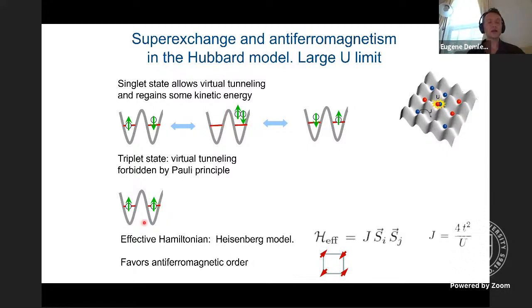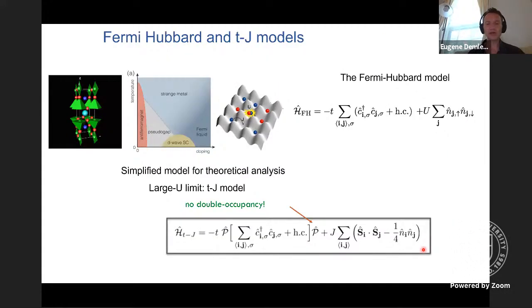On the other hand, when spins are aligned, then we notice immediately that double occupancies are just not possible by the Pauli principle, and therefore fermions cannot regain any kinetic energy. So you can do simple perturbation theory and realize that you can capture this physics by saying that when we have 2 occupied sites next to each other, there is an antiferromagnetic interaction between them that scales as t squared over U. That is what we put into this t-J model. We eliminate double occupancies, but we take them into account virtually because they give rise to this antiferromagnetic superexchange.